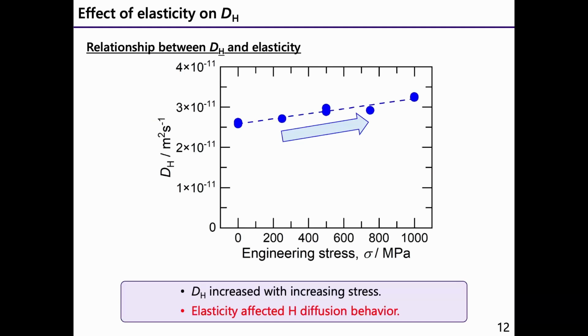Based on the result of hydrogen permeation current, we also calculated the hydrogen diffusivity, and the relationship between hydrogen diffusivity and elasticity is shown here. Hydrogen diffusivity increased with increasing stress. It means that elasticity affected hydrogen diffusion behavior.